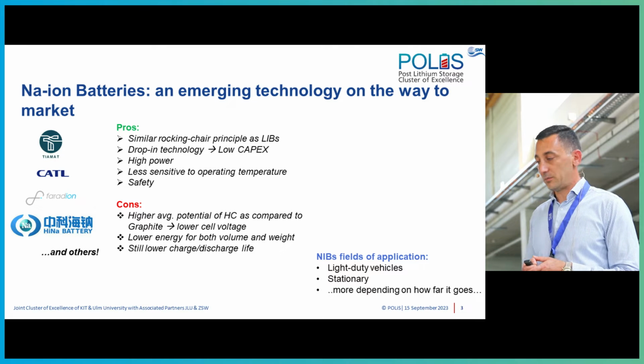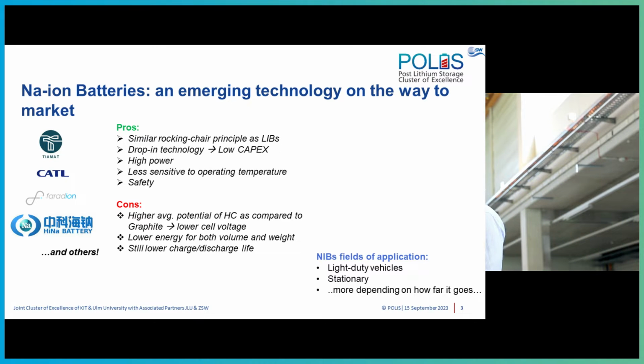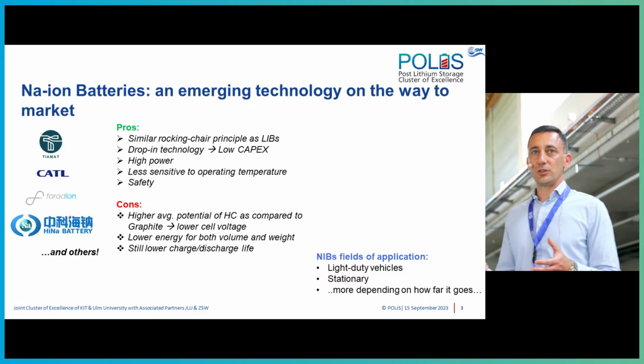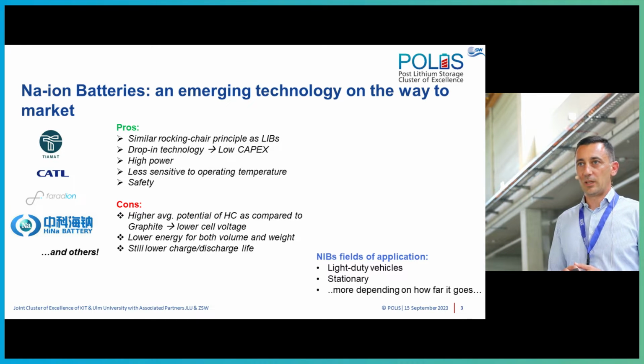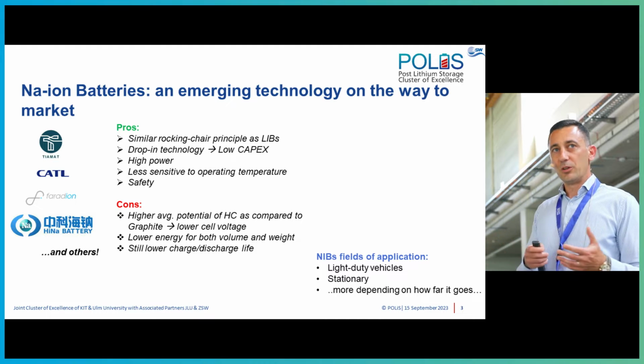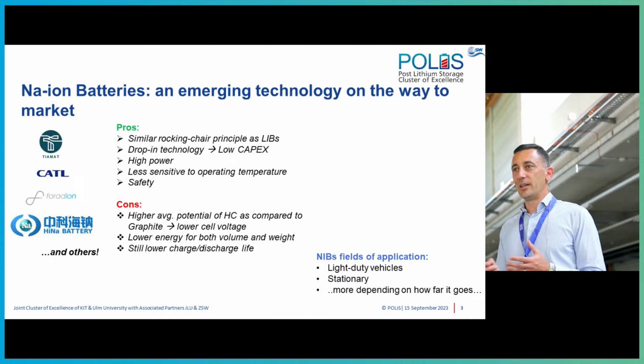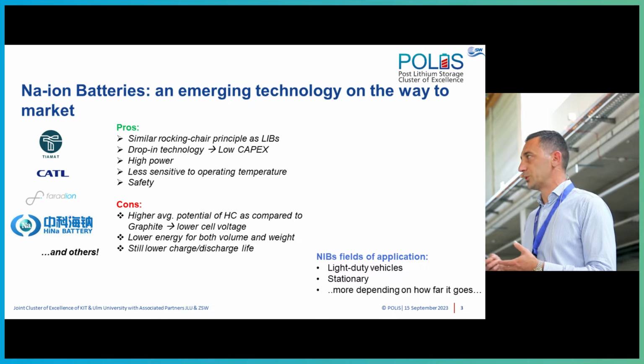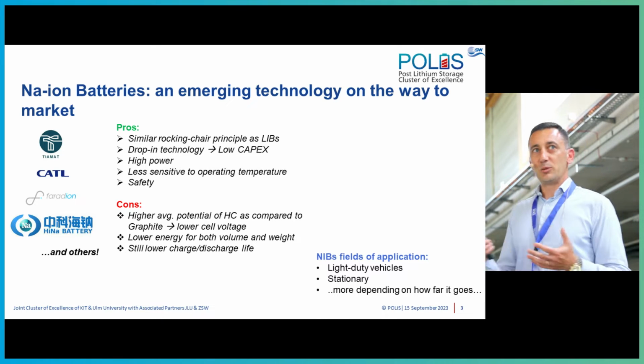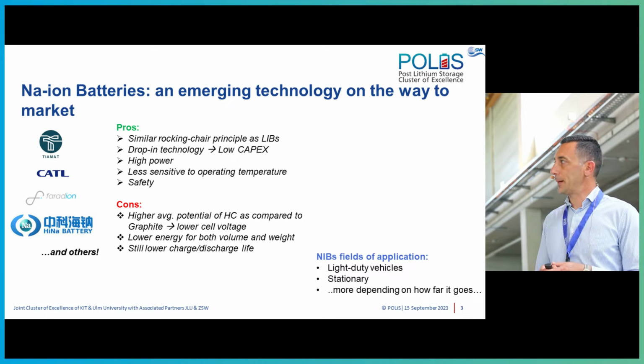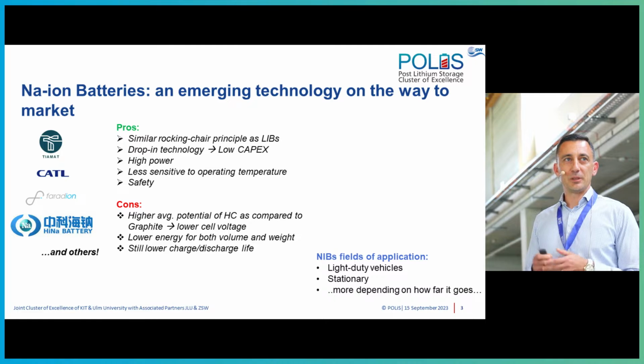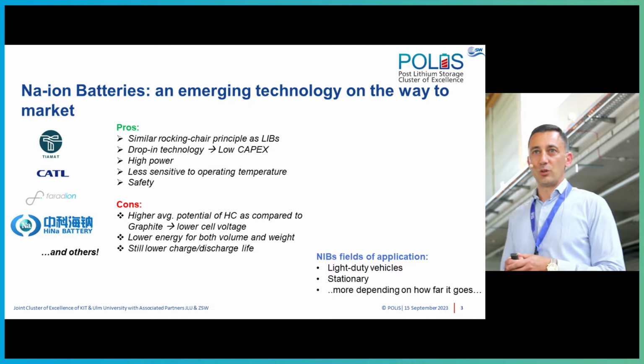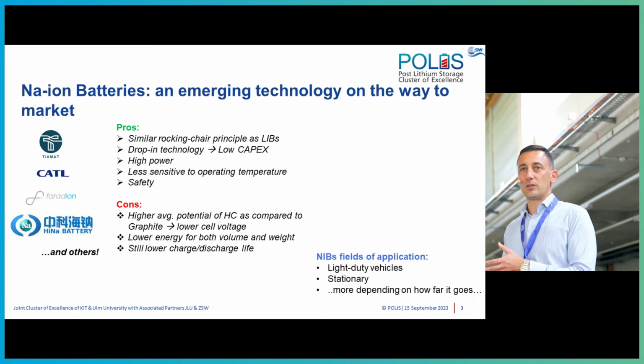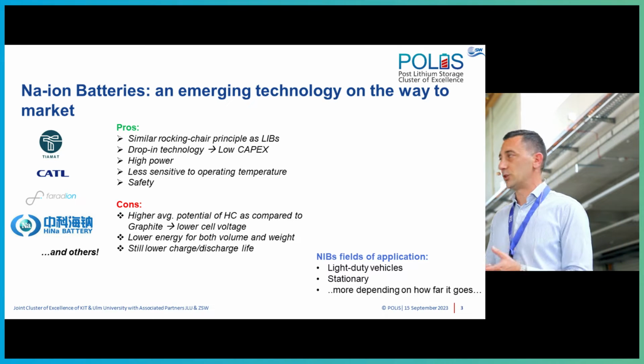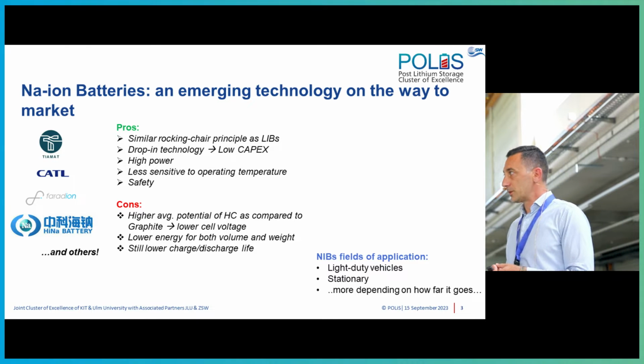And also safety. One of the good things about sodium-ion batteries with respect to safety is that they can be completely discharged and shipped. This doesn't work with graphite. You always have to have about 30%. This is what they recommend, and then you can ship the cell. Otherwise, you will have problems with SEI destabilization, let's call it that. But apparently, you can ship a sodium-ion cell even at 0 volt. And this has a direct impact on safety, because basically you have a completely uncharged cell.